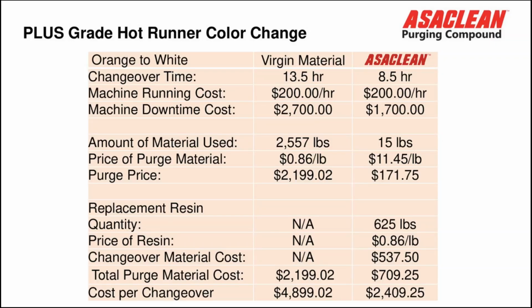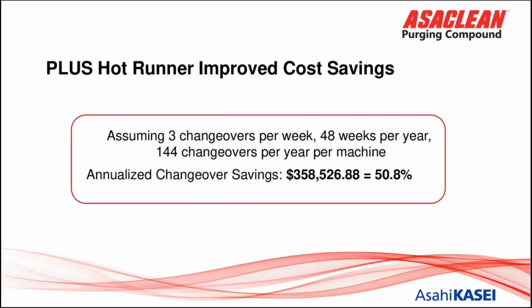Here again is a situation where we're using Plus, which is the concentrate, in a hot runner color change. This is pretty dramatic. 13 and a half hours for their way versus 8.5 hours our way. You can see the machine downtime cost is $2,700 versus $1,700, savings of $1,000 right there. And if you take a look at the overall savings amortized out, in this particular application, we're saving over 50%. And at 144 changeovers per year per machine, man, that's $358,000 we just put back into your pocket. So little things, little changes make huge differences. Not to mention the additional machine time we're giving you back to make saleable product.